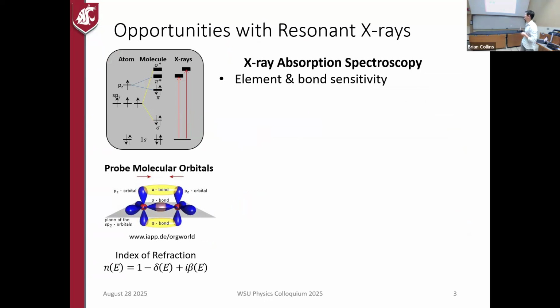So just to give you the mechanistic background here, we have, say, a carbon atom and the electronic states, and when they bond together in a molecule, they'll hybridize, and we'll get some pi and sigma bonding states, as well as the anti-bonding unfilled states. And what we do is we come in with X-rays that are tuned in energy to a transition in these molecules that promotes, when they absorb, one of the electrons from the still atomic-like 1s state up into the anti-bonding states of the molecule.